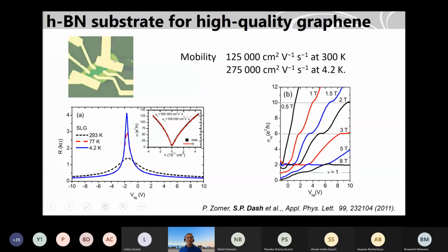So this is a boron nitride substrate. It's a flake, and there is also a graphene flake here, and we put contacts here to measure this quantum Hall effect. As you see, the Dirac point looks very sharp here, very close to 0. Still, we have some doping because the top surface of graphene is open. So we just have the substrate as boron nitride. But we have to do some cleaning procedure here because graphene is not encapsulated completely by boron nitride.